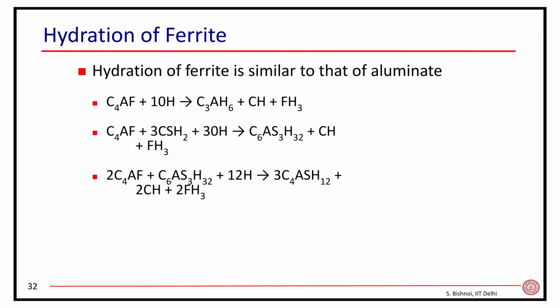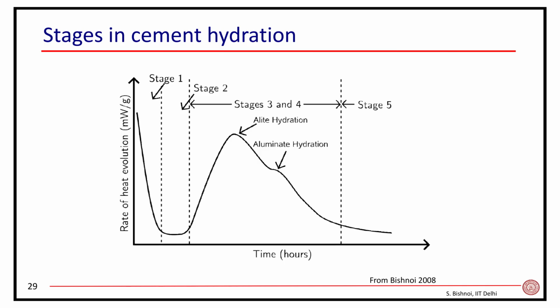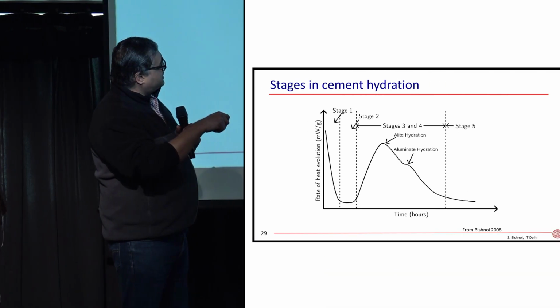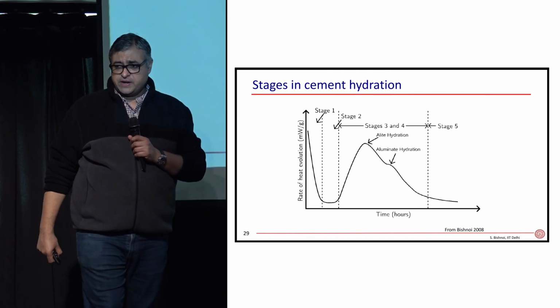So it's very important to have the right amount of sulfate depending on the amount of alumina. One quick, simple way of checking if you've put the right amount of sulfate in your cement is to carry out this test known as the isothermal calorimetry test.